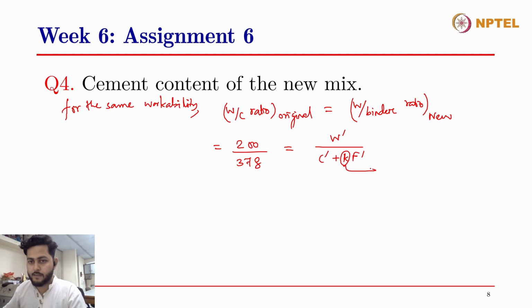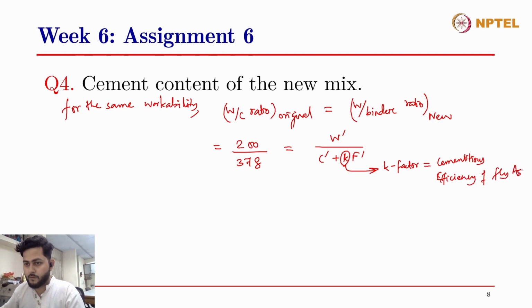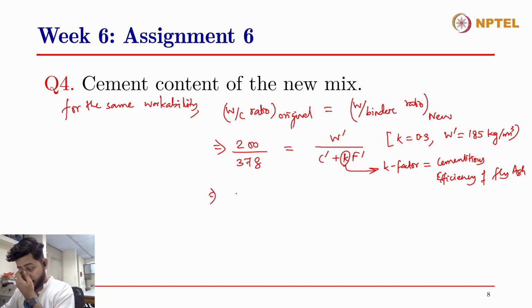So this K is the K factor, which is the cementitious efficiency of fly ash. And we know that K is given to us as 0.3, and the new water content we have already calculated in the previous question, that is 185 kgs per meter cube. And from that we can get our first equation of this problem, and that will be C dash plus 0.3 F dash equals 349.65. That is our first equation.